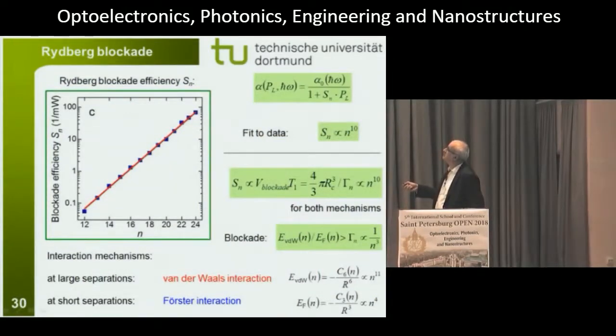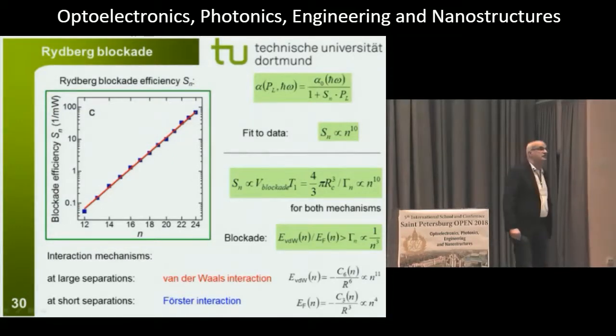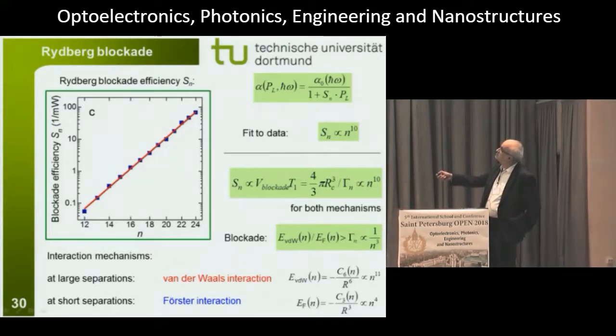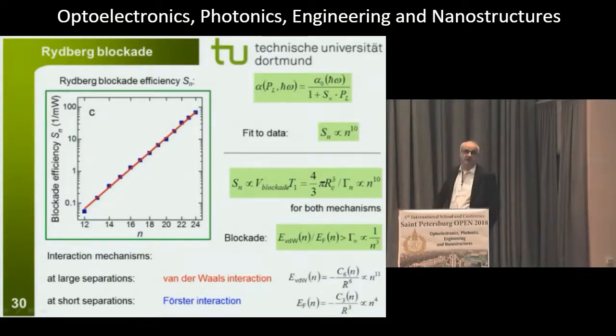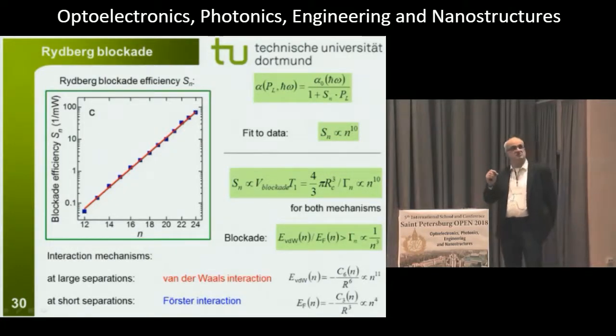So shown here are the states from n equals 12 up to 24. This is a double logarithmic plot, so you see that the data points follow a power law. And it looks not very interesting, but when you look at the numbers here, this blockade efficiency increases from n equals 12 up to n equals 24 by 3 orders of magnitude. And when you fit a power law to the data, you find that the blockade efficiency scales with the 10th power of the principal quantum number. So this is an extremely strong scaling law.